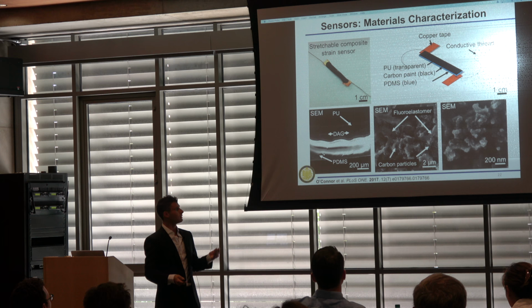So we wanted to characterize our sensors. We put the sensors on the back of the glove. In this one in particular, it is on the back of the middle metacarpal knuckle. When we formed a fist, the resistance would increase, and when we relaxed the hand, the resistance would decrease. We did a few cycles of forming a fist and relaxing the hand. We can see it goes from about 600 ohms to about 1.2 kiloohms.